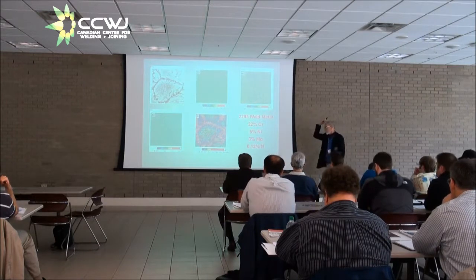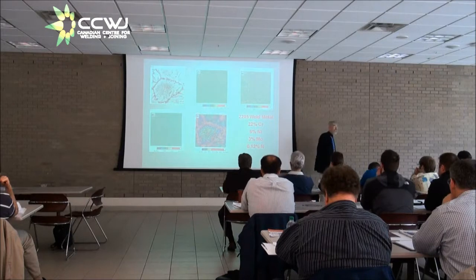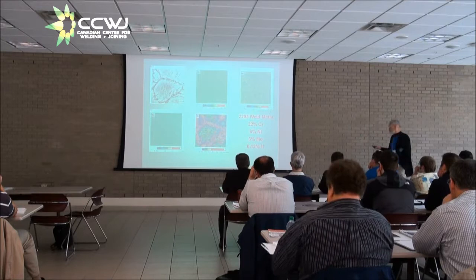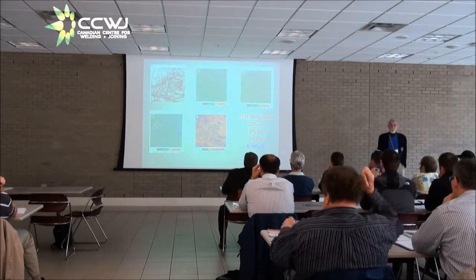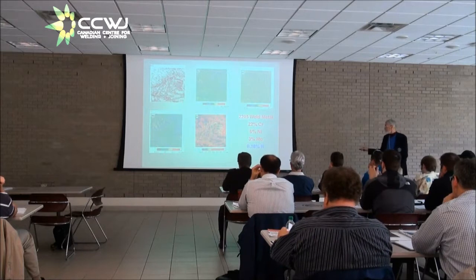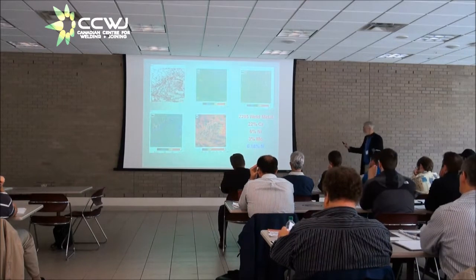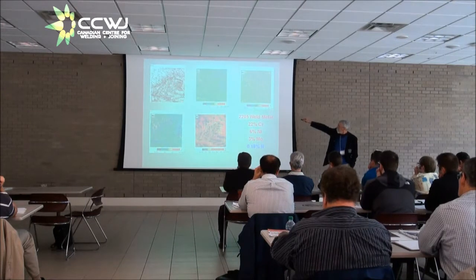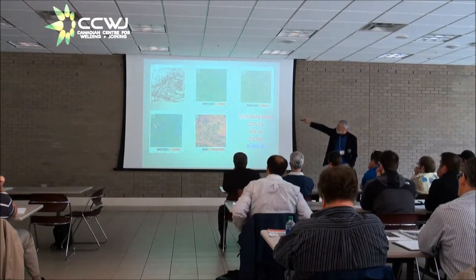Now, you might say, well, what if I wanted to get rid of those nitrides? What would I do? I might take the nitrogen out, but then I'd have a ferritic stainless steel. Yeah, 100% ferrite. A better way to go, and this was referred to by Ellen again this morning, is put in more nitrogen. Instead of 12 points now, we have 18 points of nitrogen. Otherwise, it's the same composition, 2205. Now, when you look at the base metal microstructure, you can still see a big ferrite grain outlined by austenite plates, but there are all kinds of austenite plates crisscrossing the grain internally.